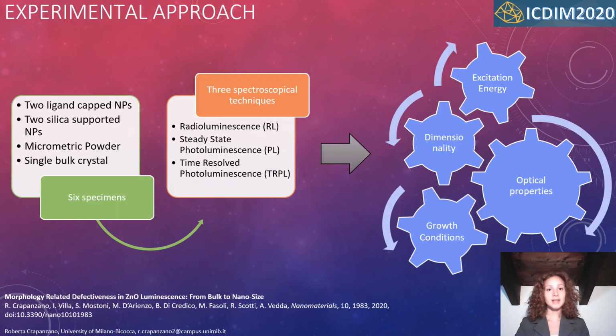To address the complex zinc oxide luminescence, our group developed a systematic experimental approach. 6 different zinc oxide specimens with dimensions ranging from the bulk to the nano-size were studied exploiting 3 different spectroscopical techniques. This analysis enabled us to evidence and discriminate the role of excitation energy, dimensionality, and growth condition on zinc oxide optical properties. First, I will present you in detail the 6 specimens and the mechanism underlying the use of spectroscopical techniques, and then I will analyze the result of this optical investigation.